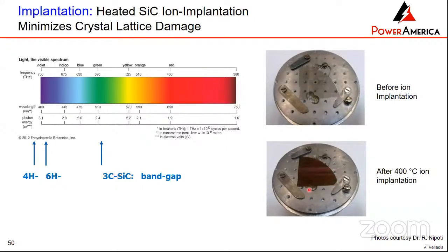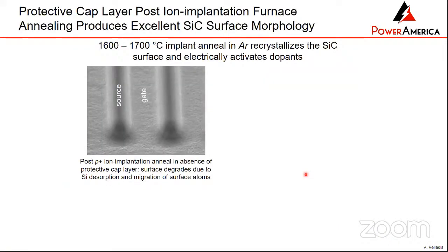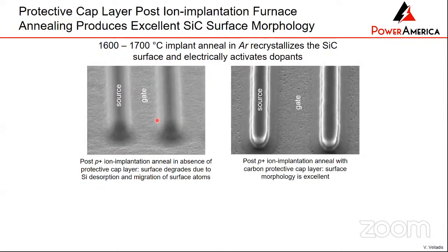In order to take care of that problem, you need to do a very high temperature anneal to recrystallize the wafer. And this is just some interesting specifics of silicon carbide fabrication. If you do the anneal of a silicon carbide wafer at 1600 or 1700 degrees, in order to activate the dopants and recrystallize the wafer, if you don't use a proper protective layer, your device will look like this. If you do use the right protective layer, then your device comes out well.